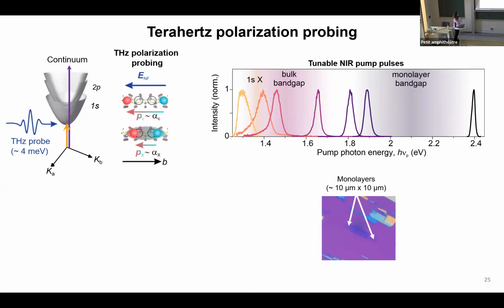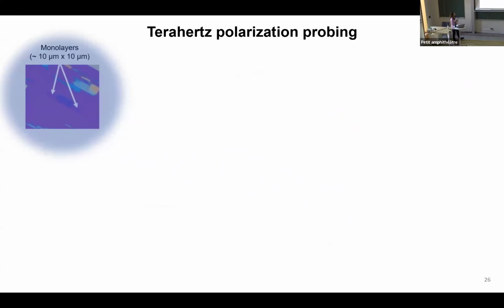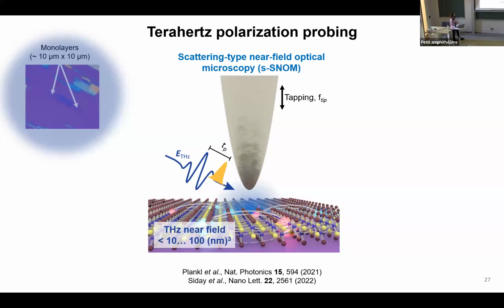But now, to convince you that terahertz radiation is even useless in this case: the size of the terahertz radiation at the focus will be orders of magnitude larger than the mid-infrared radiation, so there is no way to study our monolayer unless we can find a trick. Our trick is actually combining our terahertz radiation with the tip of an atomic force microscope and performing scattering-type near-field optical microscopy, or what people call s-SNOM. The idea behind s-SNOM is that we couple the terahertz radiation to the tip, and then this metallic tip confines the electric field of light to a region which is solely determined by the radius of curvature of the tip.